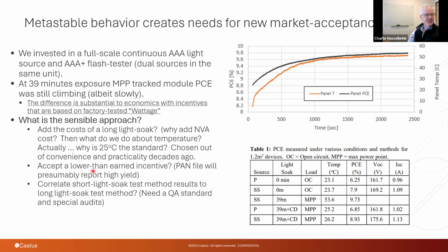Another question that comes up, of course, is, hey, would we accept a lower than earned incentive? If this is a 9.8% panel, getting only 90% of that is a possible way to go. It's not what we prefer, obviously. And our PAN file will presumably report a very high yield because, in the first hour of operation, we're going to have a panel that's operating much higher, and that may add a lot of confusion downstream in the market. So that doesn't seem very nice for that reason.